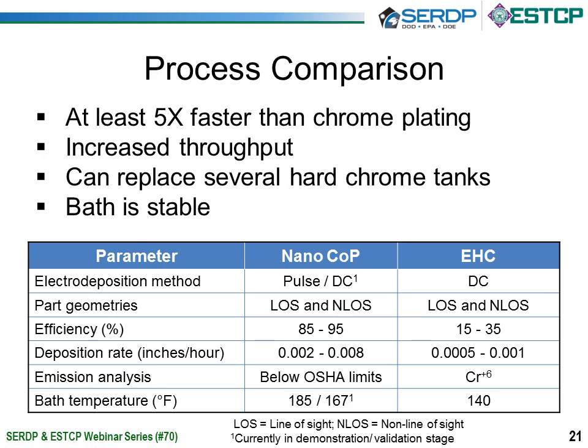A quick comparison between the processes for nanocrystalline cobalt phos and electrolytic hard chrome. One of the big advantages of the cobalt phos is the faster plating rate than chrome. It plates about 5 times faster. So this can result in increased throughput, and you can replace several hard chrome tanks with one cobalt phosphorus tank. And the bath is very stable.